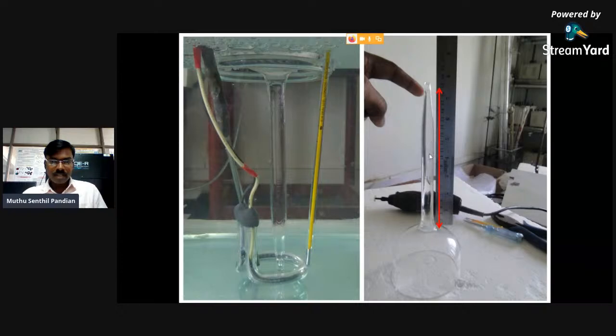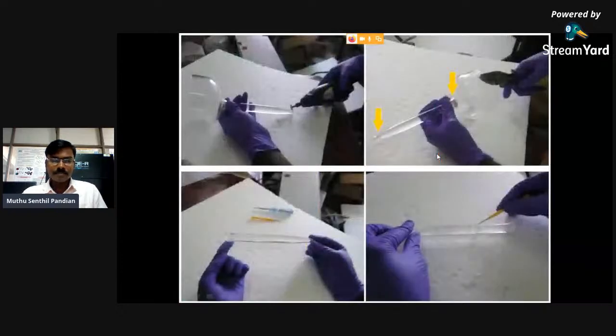So this is the SR method grown TGS ferroelectric material inside the glass sample. Now using this diamond wheel cutter, we have to remove the top and bottom portions. We have to remove these two portions. So this is the 15 centimeter long TGS crystal inside the glass sample.